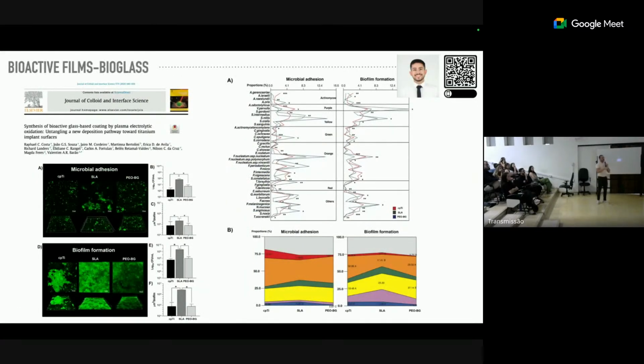We also have another surface, in which we try to mimic bioglass on the surface. We compare with the SLA surface, the commercially available one, in terms of microbial adhesion and biofilm formation. But the most interesting result here is the modulation of this biofilm. The level of red complex bacteria in the PEO containing the bioglass, plasma electrolytic oxidation, was lower when compared to the control. So you might have some surfaces that can modulate the composition of this biofilm.